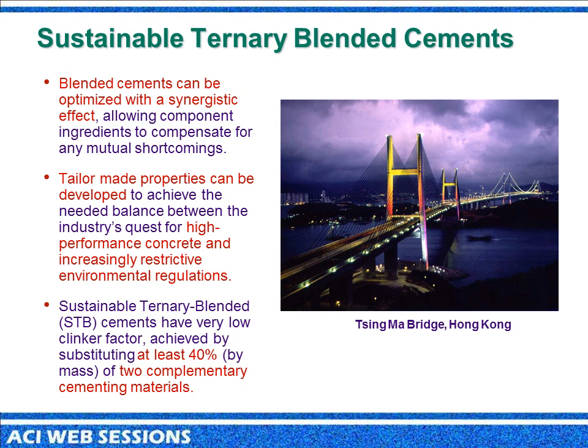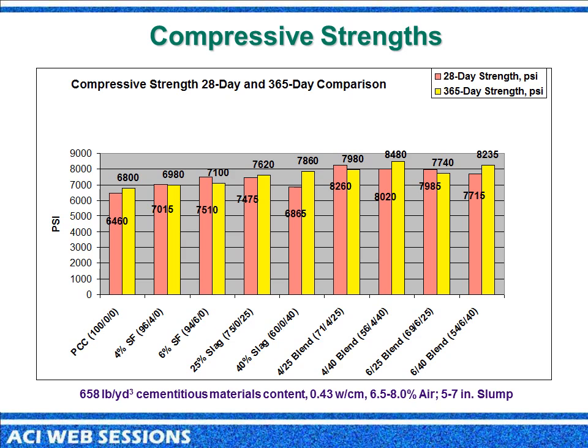With sustainable ternary blended cements, these are typically with components that are at least 40% by mass, making up the cementitious materials ratio. Here's some data that has typically been collected when we look at any concrete mixture, and these would be of compressive strength. Certainly we can see here in using the blends, and you'll see at the bottom we have Portland cement. This would be with our 4% silica fume, 6%, 25% slag. Here are our blends, 40% slag. Here's a 4% silica fume and a 25% blend. A 4% silica fume and 40% blend of slag cement, 6% silica fume and 25% slag cement, and finally a blend of 6% silica fume and 40% slag cement.